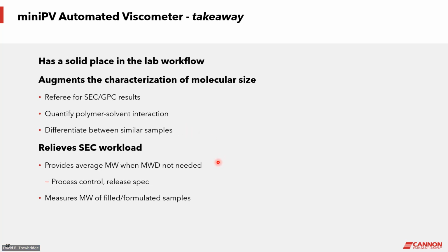Also, the IV measurement using DSV technique and the mini PV in particular gives you an opportunity to maybe offload some of the SEC work. If you're looking at an average from your SEC measurements, you're going through a lot of steps to fractionate it and then reconstruct an average. It may be better to just measure the intrinsic viscosity directly and use it to control your release specs or the processes that you're already maybe looking at a molecular weight that's not quite as reliable or has as good resolution for these control steps.